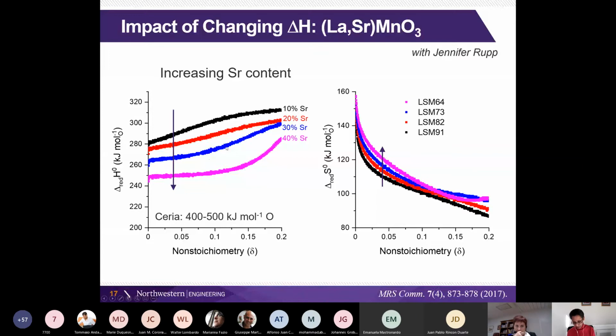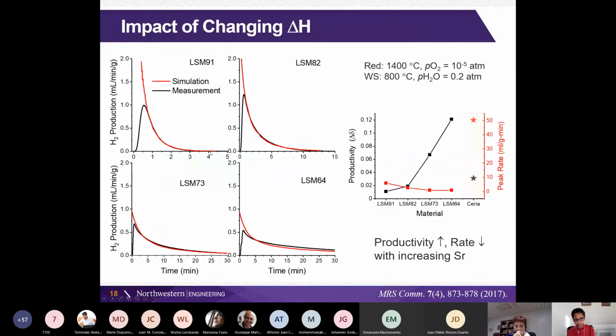And so let's look at what it does for the hydrogen production step. What we can see is that the hydrogen production is relatively fast when we have just the 10% strontium, and the enthalpy was still reasonably high. And as we go to more and more strontium concentration, we can see that the rate declines quite dramatically. And now it's taking a very, very long time.